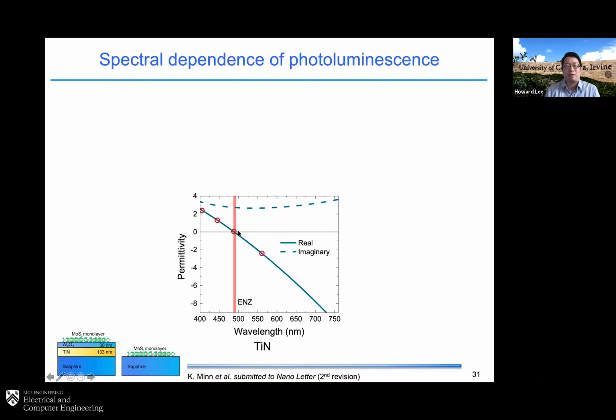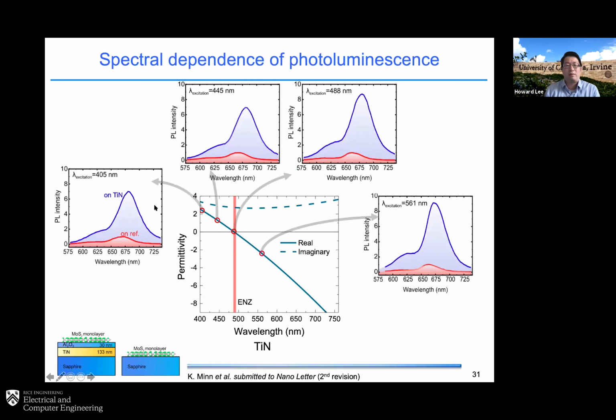But what we also want to do is look at the spectral dependency. For example, we have an ENZ wavelength around 500 nanometer. We want to see what kind of effect there is when we excite across the ENZ wavelength, on the lower wavelength side or the longer wavelength side, and how the photoluminescence changes. So what we do is take the spectrum by exciting at different wavelengths, and you can see this typical spectrum. The titanium nitride has much stronger PL enhancement compared with the reference. Then we integrate everything and look at the different wavelengths, basically looking for any enhancement because of the ENZ film here.